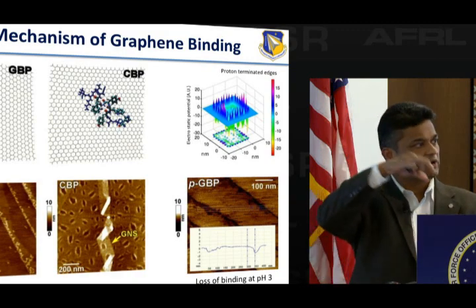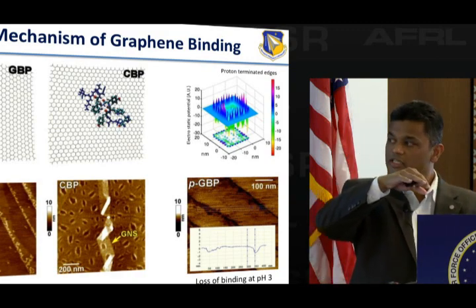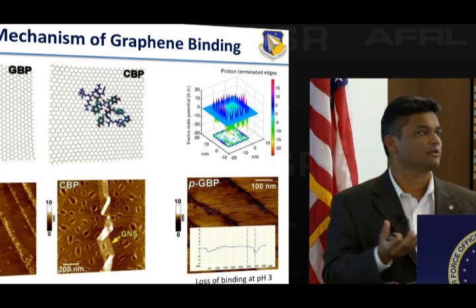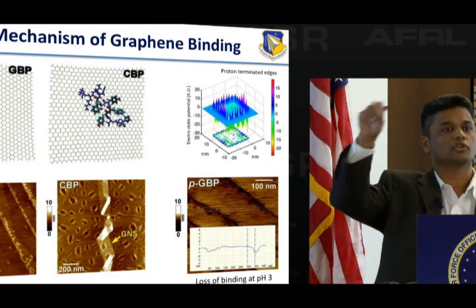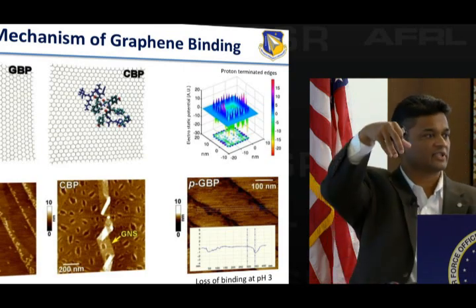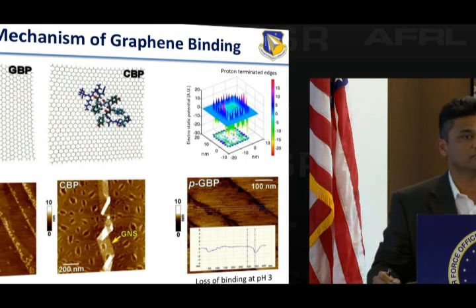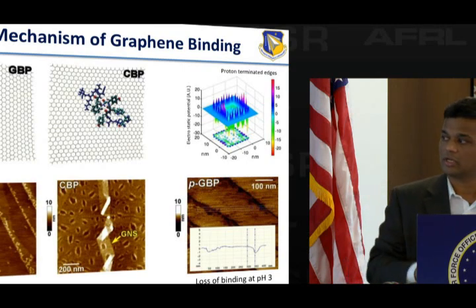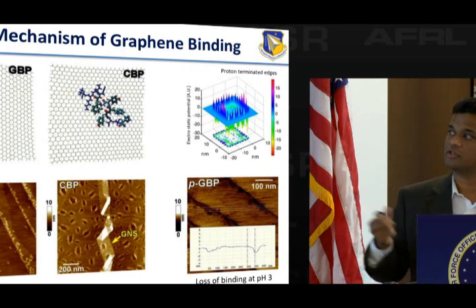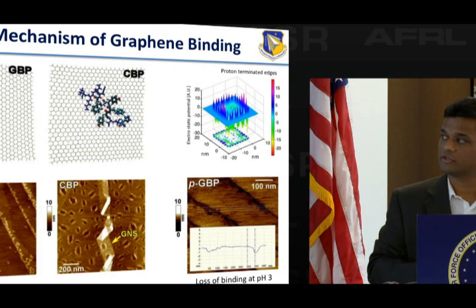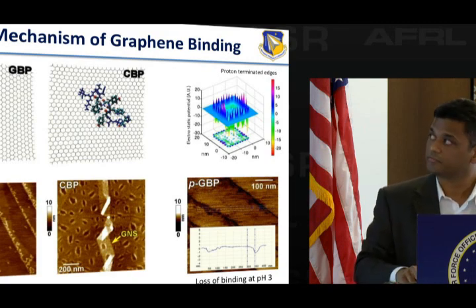We know the peptide, when it binds to the graphene structure, tends to assume some kind of secondary structure. So it's random in solution, but then when it sees a surface, it actually forms a very unique secondary structure, and that gives rise to tertiary structures that you will see formed on the surface of the graphene sheet.